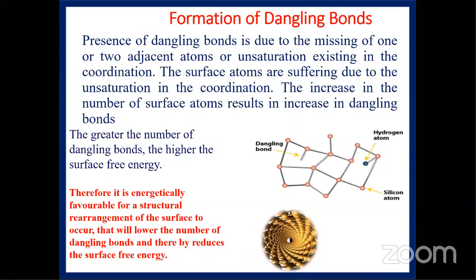And third, this is also quite interesting, the formation of dangling bonds. That means missing of one or two adjacent atoms, or unsaturation existing in the coordination. That is called a dangling bond. In these dangling bonds, the surface atoms suffer due to the unsaturation in the coordination. Increasing the number of surface atoms results in increasing dangling bonds. So the greater the number of dangling bonds, the higher the surface energy.